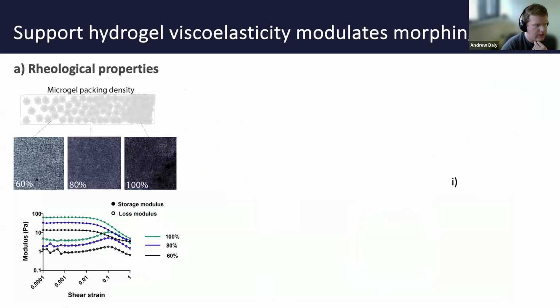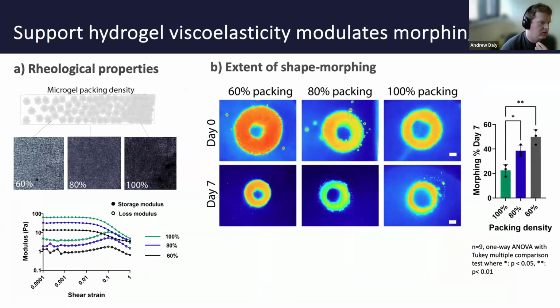I'll go through this quickly, but the other interesting thing that we noticed is we're printing these tissues in a viscoelastic support. And we found that the viscoelastic properties of that gel that the tissue was printed in also impacted how much it could shrink. If we had something that was more viscous, so more liquid-like, versus something in the last panel here that's more elastic or has more energy storage, we saw that there was less shrinkage within the tissue, because it's providing more resistance to the morphing over time. So that'll also have an impact on the process. So we can print something, we can predict it, and it'll morph over time.